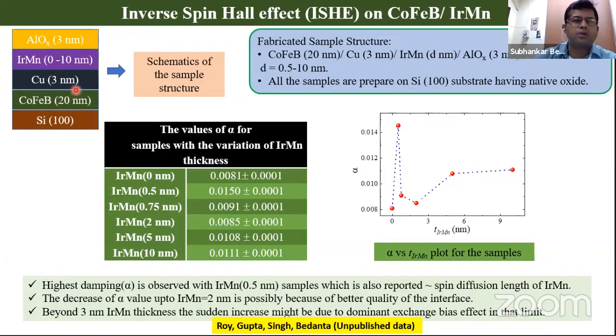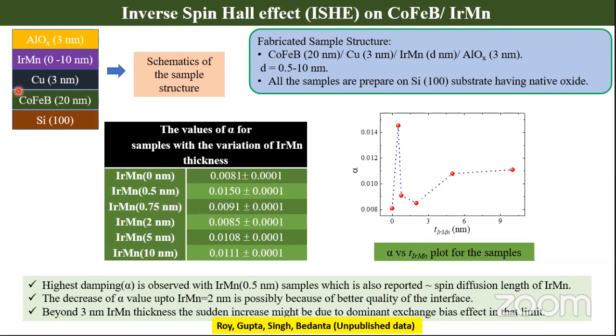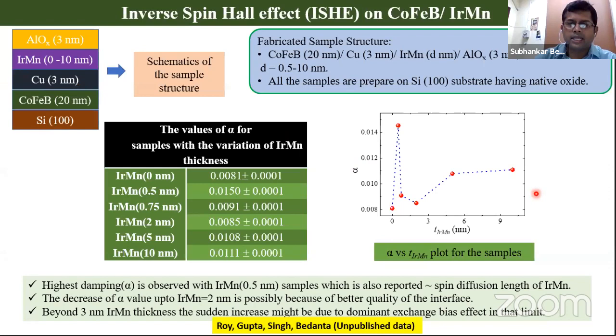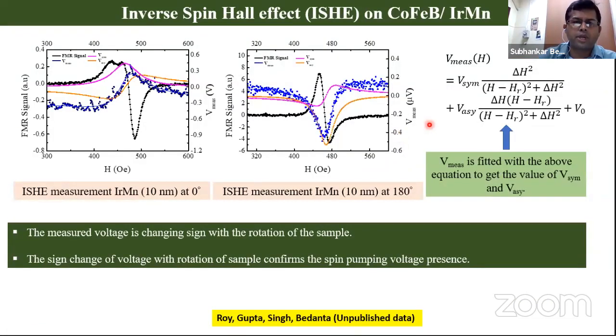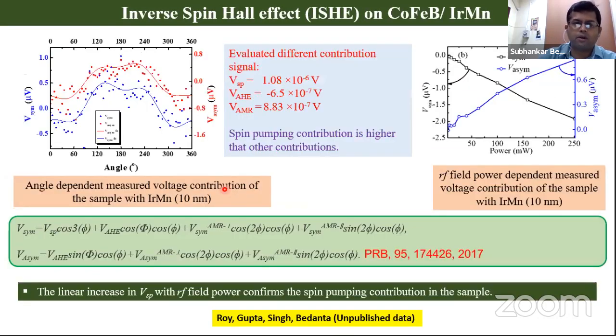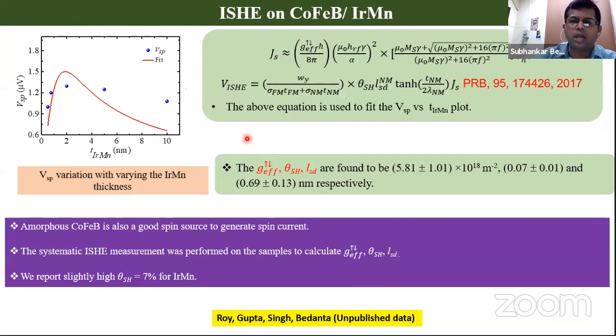Okay, fine. So then you measure the damping constant for the single layer of cobalt iron boron and the bilayers, and you plot this, and you find there is an enhancement of damping constant for about 0.5 nanometer, and that goes very well because in the literature for iridium manganese the spin diffusion length is about 0.5 nanometer, and that we kind of show. And further we also did the ISHE measurements, and we decomposed, and we found the spin pumping voltage is higher compared to other spin rectification effects, and we found that the spin Hall angle for our system is a little bit higher than the reported value, where they have taken permalloy as a ferromagnet and we have taken cobalt iron boron. However, the spin mixing conductance is comparable, 5.8 times 10 to the 18. That's in the same order as reported values, and the spin diffusion length is about 0.7 nanometer, which is also in the same order.